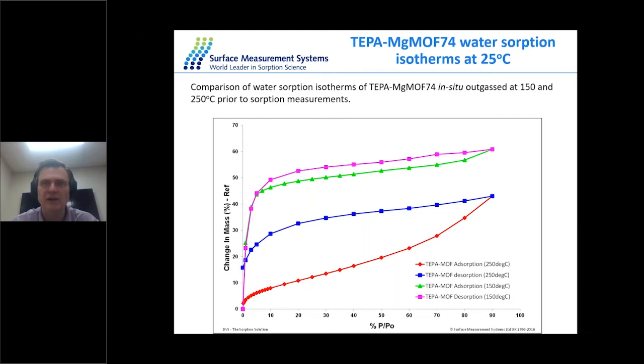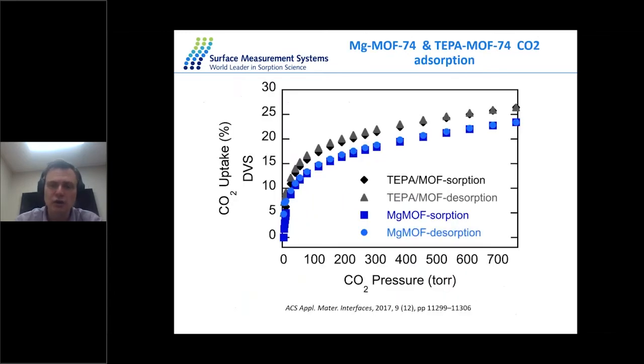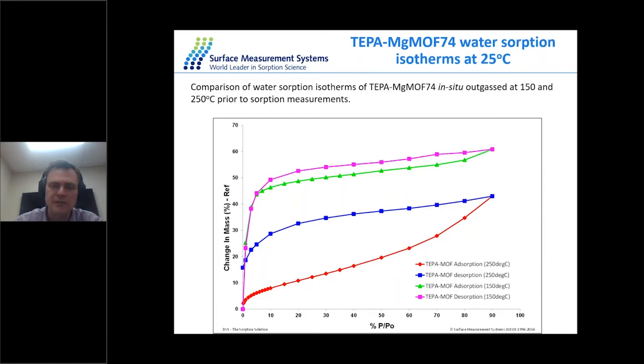is that we can see sometimes different MOFs showing different adsorption capacity in the scientific publications, and in many cases this can be attributed to the chemistry or preparation methods. But I think we should consider, as a wider community, also looking at the outgassing conditions, how the materials are treated before the adsorption study, because as can be seen here, the effects of the outgassing can be quite significant. I mean, typically you would never outgas below 150 degrees. But again, if you go too low, to much lower temperatures, you're going to see